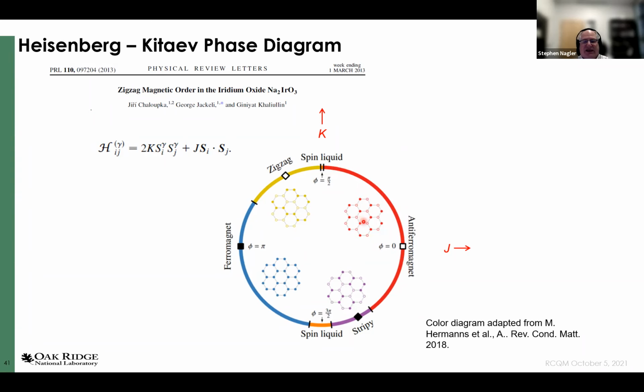And again, this being a bipartite lattice, this is not frustrated in the conventional sense, right? If it's ferromagnetic dominant, you'll see a ferromagnetic lattice. And then depending on the ratio of ferromagnetic or of Kitaev to antiferromagnetic, I can get 2 other structures that are actually antiferromagnetic but different, the zigzag structure and the stripy structure.